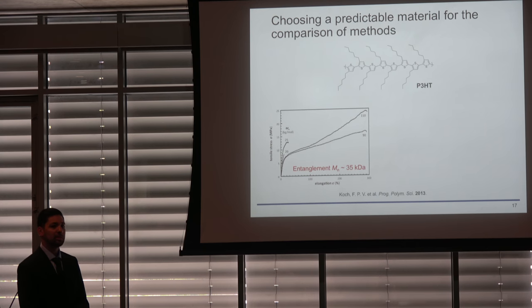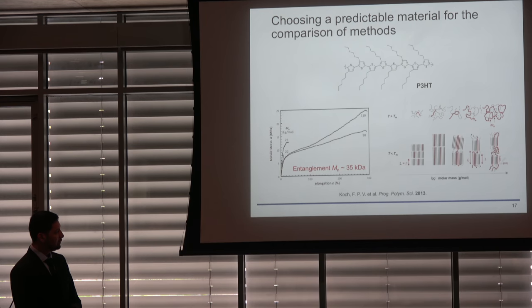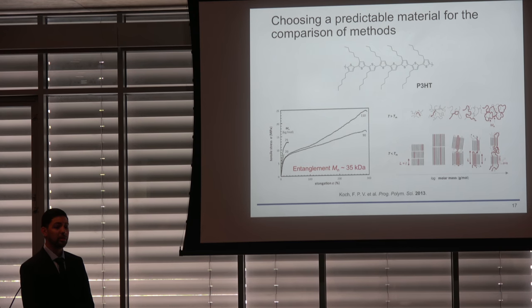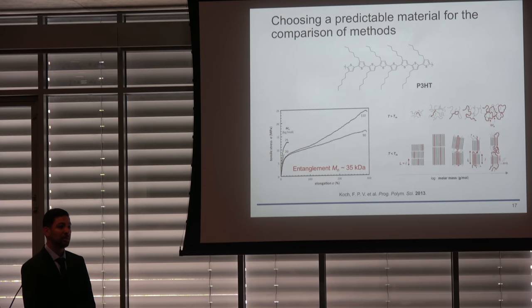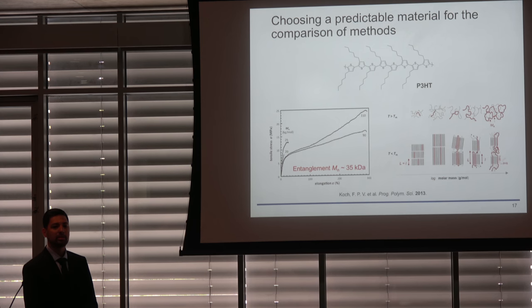Above the entanglement molecular weight, polymer chains are physically linked—they can slide past but not through each other, like knots within the film. At low molecular weight, polymer chains behave as short rigid rods and easily slip past one another. At high molecular weight, chains are highly entangled. In crystalline regions, low molecular weight chains form chain-extended lamellar crystals, while high molecular weight chains can loop upon themselves to form multiple crystals, creating 'tie molecules' that improve connectivity. Overall, high molecular weight improves connectivity in polymer films through entanglements in amorphous domains and tie molecules in crystalline domains.